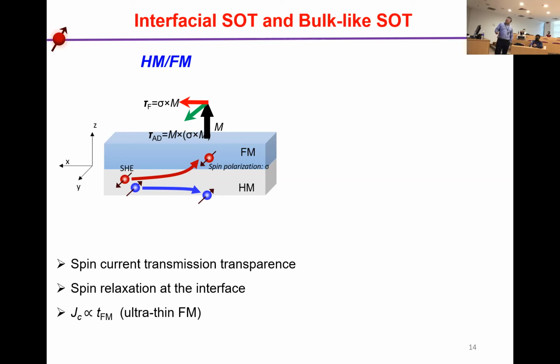So in order for high density, we know we need a thermal stability factor which should be larger than 40 to 60, depending on the time the data is stored in the bit. For 10 years, we need it larger than 60. The thermal stability factor is equal to KUV divided by KBT, where V is the volume of the recording bit. That means the ultra-thin film needs a larger bit size, so it's not favored for ultra-high density.